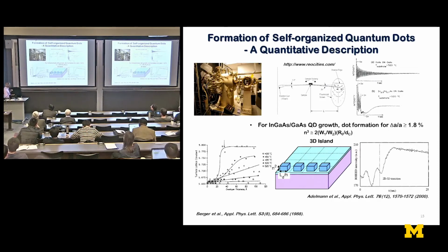And of course, as you lower the temperature, the kinetics is not there, and it cannot reach the critical thickness. So we realized that under these conditions, you have a three-dimensional growth mode even before the critical thickness is approached. And this is an equilibrium phenomenon, but the formation of these dots is kinetically driven. In fact, my colleague Jaspreet Singh, based on energy minimization on the growth surface, came up with this very simple formula for n cubed, the number of monolayers, the height of these dots, which depends on the ratio of the nearest neighbor and second neighbor bond energies, and the critical thickness, and the substrate lattice constant.